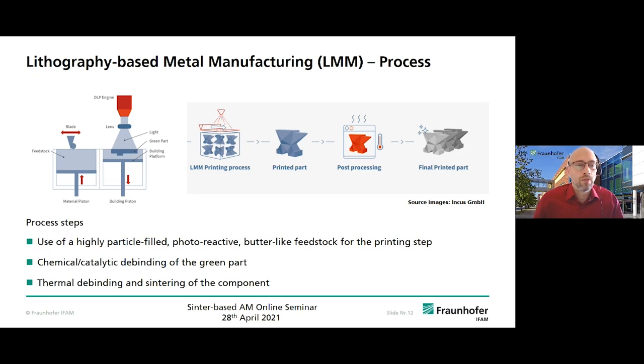The third process I want to very quickly show is the lithography-based metal manufacturing, or LMM, process. This, as I mentioned, is the latest addition to our facility in Dresden, and you can see that it's a little different from perhaps what you know from the ceramic field LCM process. You have a feedstock which is more like a butter-like paste, and with a blade you pull it over onto your building platform where you put a beam of light by a DLP engine onto your part, and where the white pixels hit the material, the chemical reaction will occur, and where the light or the picture is black, the material won't harden.